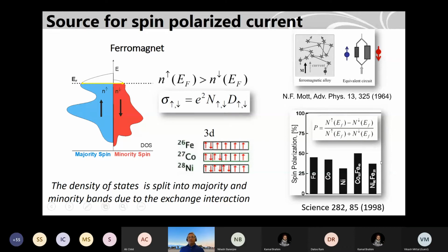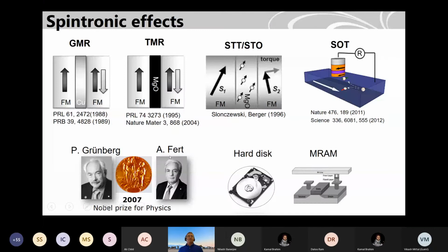And you can find other materials with 100% spin polarization, but they are mostly at low temperature. And these measurements were done with superconducting point contacts. A superconductor in the gapped state is 100% polarized. So if you put a point contact with another ferromagnet, you can find the spin polarization. These things helped Peter Grünberg and Albert Fert to discover the giant magnetoresistance. So what is the giant magnetoresistance? I'll come back to that after this slide.